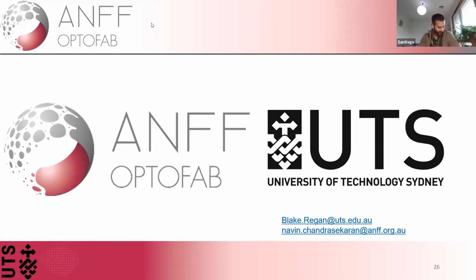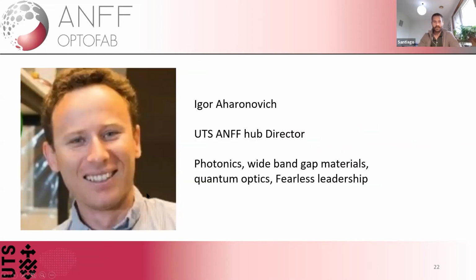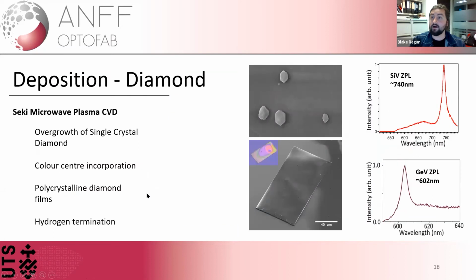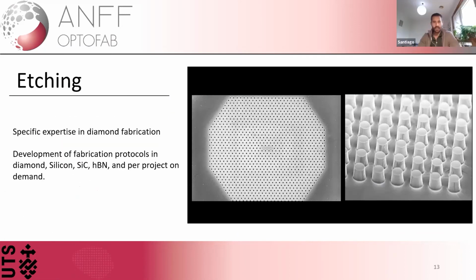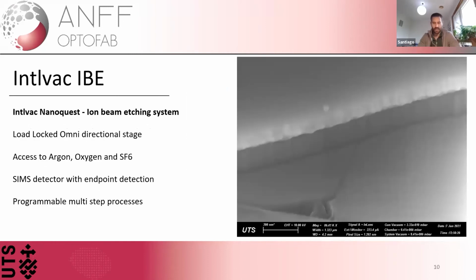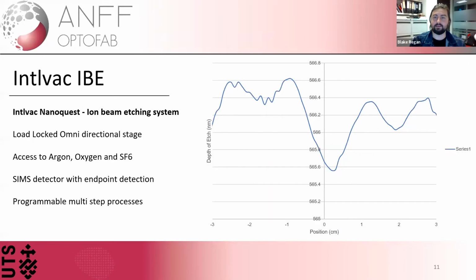Sorry, Santiago here. Thanks very much for the presentation. I was very impressed with the results you show about reactive ion etching and that low roughness. Can you elaborate on that and provide a bit more detail on the sample? So was this the reactive ion etching or the ion beam etching? The ion beam etching in that case. It was the 1 nanometer or 0.5 nanometer. Okay, so that was with the silicon substrate.